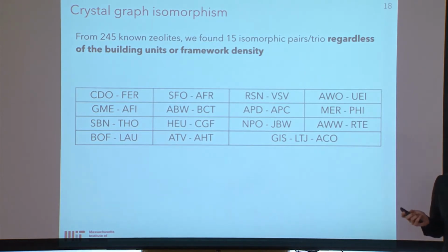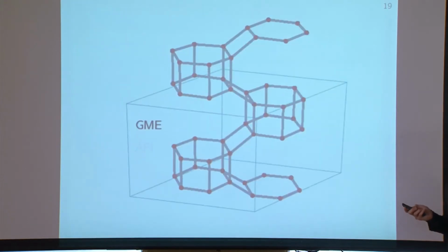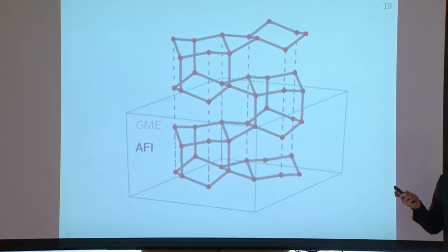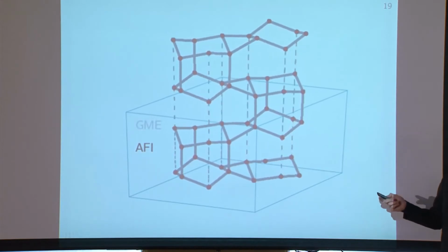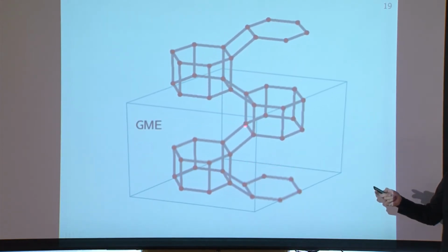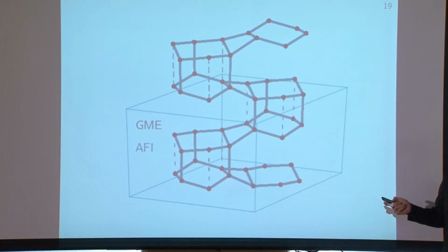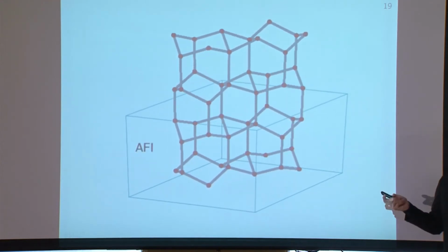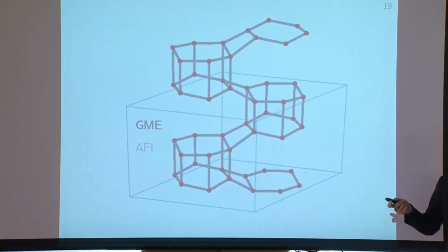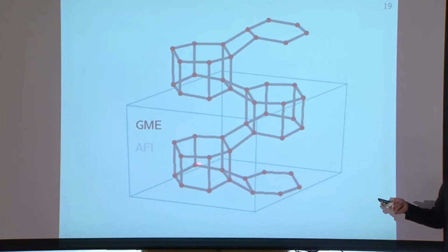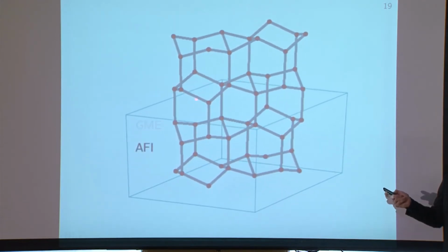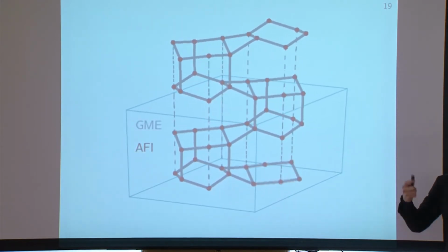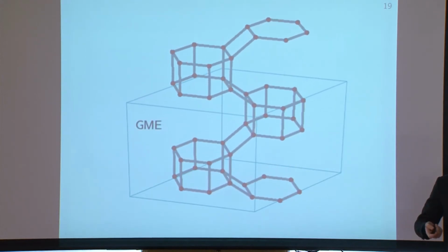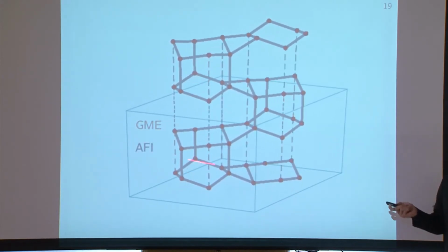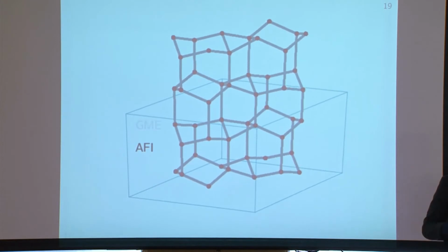Take the example of Gmelinite zeolite converted into AFI zeolite upon heating. This is the process that happens to that crystal structure. You heat up Gmelinite, you shrink the C direction of each unit cell, break some bonds, and reform them. But you do it in such a way that the bonds which are broken are reformed with the same atoms when the periodic boundary conditions are taken into consideration. So these two crystal structures share the same graph representation.